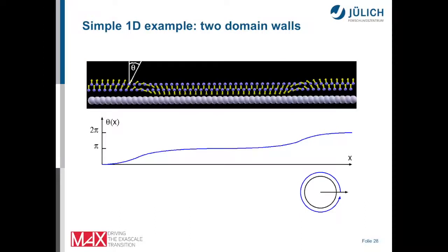Now, in reality, this can occur in simple magnetic arrangements like domain walls. So I'll show you here a double layer of iron on some substrate, and show here a Néel-type domain wall. You can see that the magnetization rotates clockwise from domain A to domain B, and then there is a second domain wall that rotates again clockwise from B to A, and you can now describe this structure if you plot the magnetization direction as a function of x coordinate.